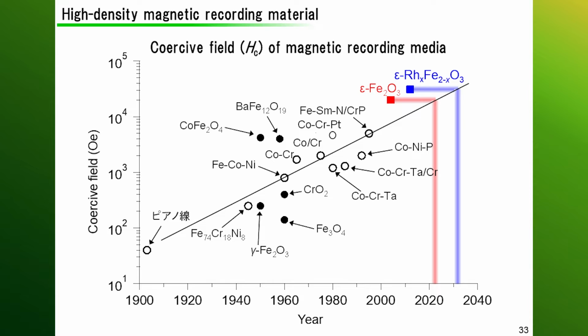What are the possible applications? The graph shows coercive field strengths vertically and Western calendar year horizontally, representing coercive field of magnetic recording medium. There has been a growing need to increase recording density. Here are the epsilon iron oxide and rhodium substituted epsilon oxide. It is expected that these materials will contribute to satisfying the need for recording requirements in 2020s and 30s, especially in the use of magnetic tapes.